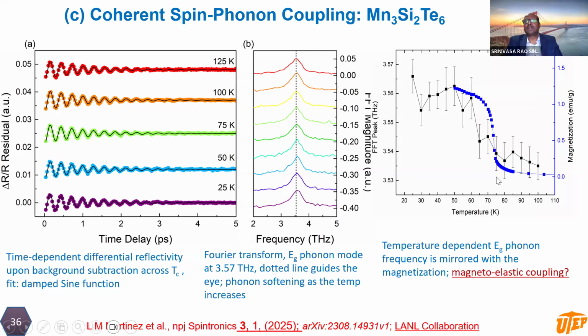So that shows that these materials show strong spin-phonon coupling, and we extracted that information by applying optical pump-probe pulses, and most likely that is due to magnetostriction or magnetoelastic coupling. There's a debate going on in the literature, but we believe that there is a magnetoelastic coupling this material provides upon photoexcitation. Basically, we are distorting the crystal, expanding the crystal upon photoexcitation.